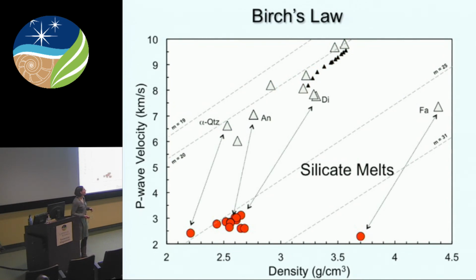Okay, but if we look at silicate melts, what we can see is that regardless of their density here, they have a very narrow range of P-wave velocities. This is not what we would predict by Birch's law. And you can see here these lines where I've linked the crystalline and liquid phases. You would project, because these have lower density, that they should follow along these sorts of trends. And you can see that really they're cross-cutting. And what's really interesting is that you can have this really wide density range and still have these very narrow velocities.